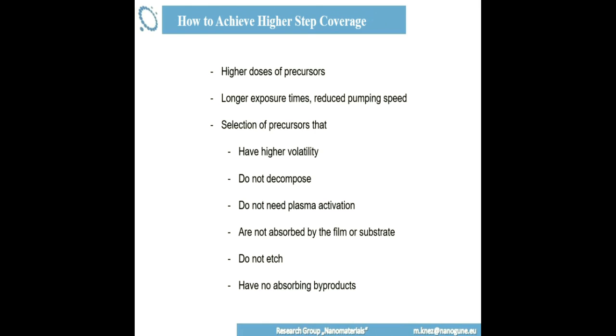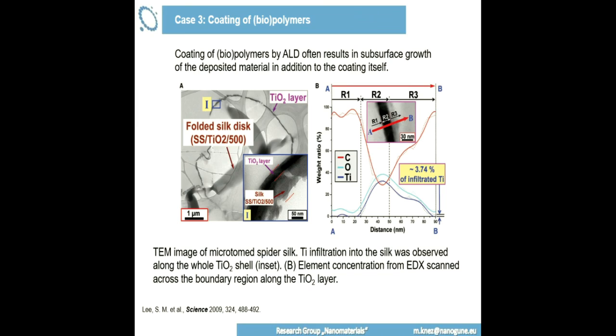Oh, I thought that would be further. Okay, so we had the step coverage, the pores, we had the surface diffusion. These two things happen during an ALD process, and there is a third one which can happen during the ALD process. Again, substrate related. First we had inert substrates, then we had porous substrates. The third one is, and this is going to affect many of you, if you have polymeric substrates. If you have a polymeric substrate and you want to do an ALD coating, what can easily happen, like in this example, so this is a biopolymer, but it really doesn't matter too much.